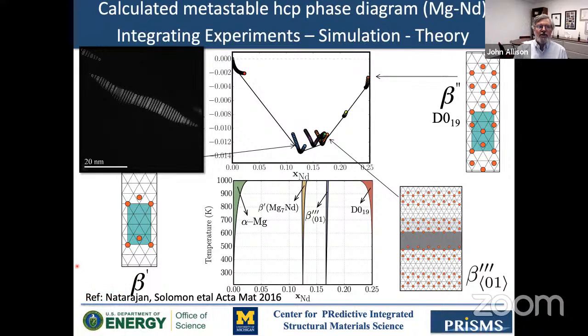So anyway, in the center of this figure, the primary precipitates that we're thinking about here are metastable precipitates. So we can't use CALPHAD because these particular rare earths have not been assessed in the metastable phases. And in these Mg-rare earths, there's an enormous amount of controversy about the precipitation sequences in these alloys because they're very, very complicated. So we looked at Mg-neodymium and Mg-yttrium as sort of our prototypes for where to start.